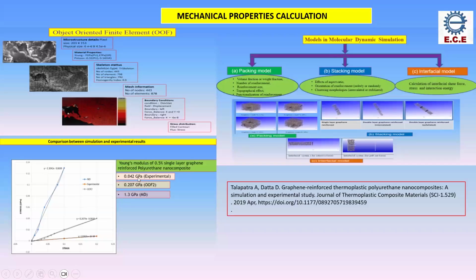nanocomposites are 0.04 gigapascal. In object-oriented finite element, it is 0.207 gigapascal. But if you go to the molecular dynamics simulation, it is much higher. You can see that molecular dynamics simulation gives much higher values compared to the finite element methods, because the finite element method is nearly the experimental value, but molecular dynamics simulation gives the atomic-level property. It always comes out much higher compared to the real material. But what is the advantage? You can get the idea about that material.